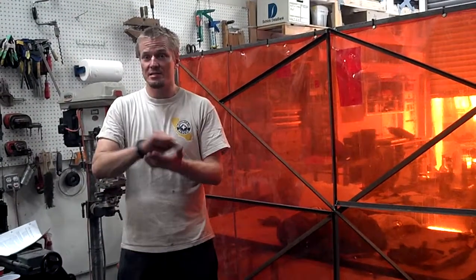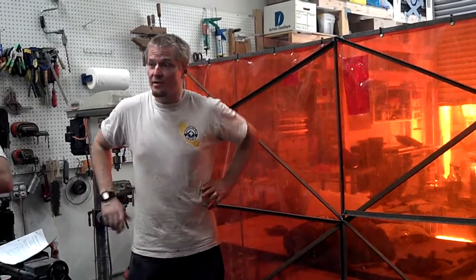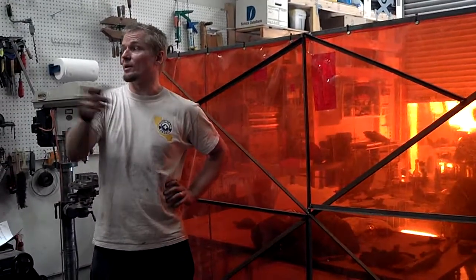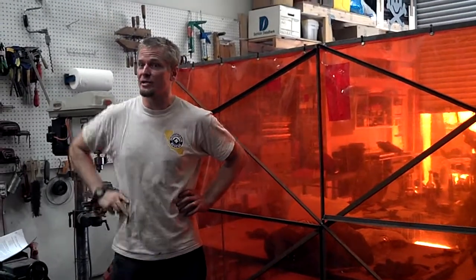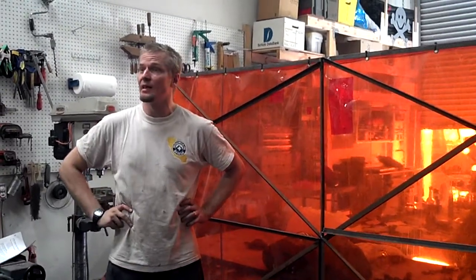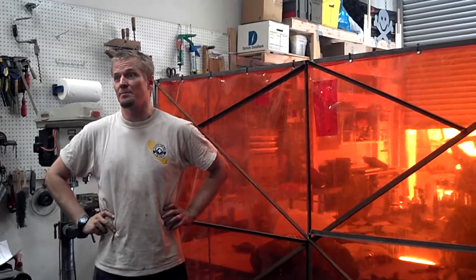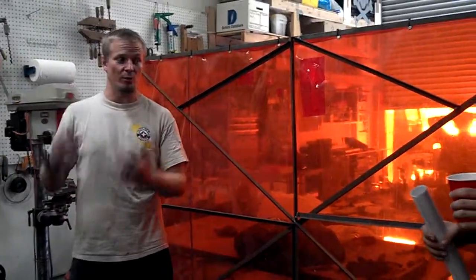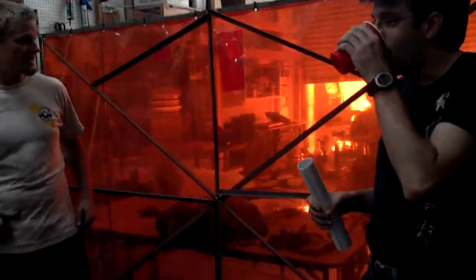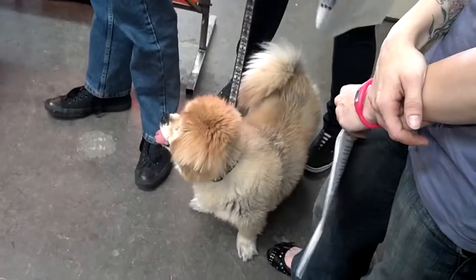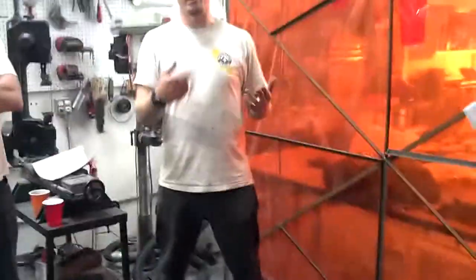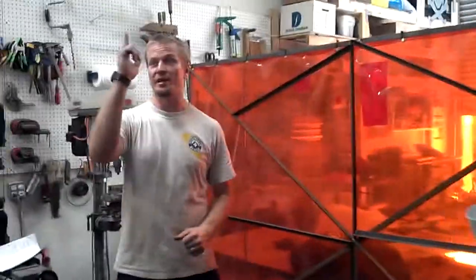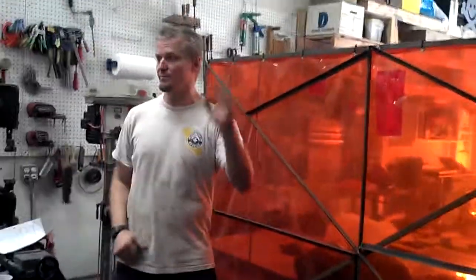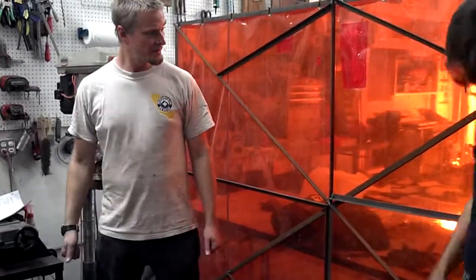It basically makes a shielding gas and a little bit of slag. Now, it's actually not legal to use MIG welding outside for structural fabrication in most places by code and whatnot. Because if wind comes up, it could blow away the shielding gas and make a poor quality weld, and you might not know it. Whereas if you use that flux core wire, there's always enough of that flux burning to keep it shielded and safe.